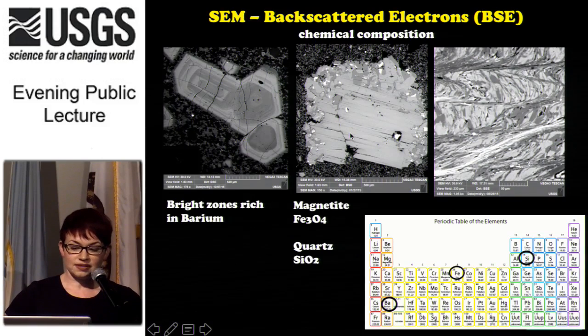The middle image is a biotite mineral grain, and you can see around the edge, it's breaking down into its oxide components. The very bright white ones are magnetite, or iron oxide, which is down here, and these darker gray ones are quartz, so SiO2, which is here. The iron is heavier than the quartz, so it's going to show up much brighter. This kind of texture shows us that this mineral experienced either depressurization, so a rise to the surface, or a loss of volatiles, or both. So it's just an example of the kind of things we can learn from BSE.